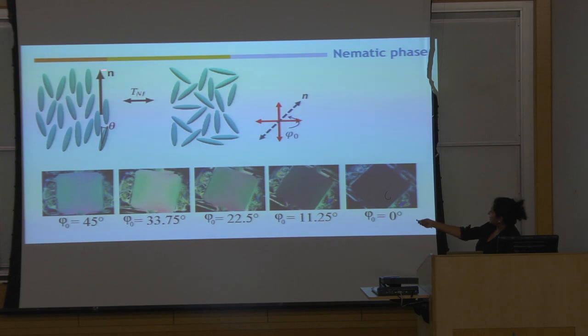So the ordering is such that N is oriented like that, and the image appears bright. What's happening is the light that's going through the first one, half of it makes it through the liquid crystal, another half makes it through the bottom one, and we get some light out. When we rotate the sample between the polarizers, the intensity changes till it becomes black when this N orients with any one of the cross polarizers. So you can think of the liquid crystal nematic material acting like another linear polarizer. And that's how you can tell. If this liquid crystal here was like that, it would appear black all the time. It would not change with change of angle. So that's our test. That's how we know we have a nematic phase or not, we have order or not.